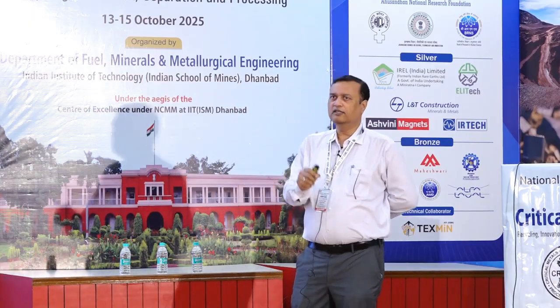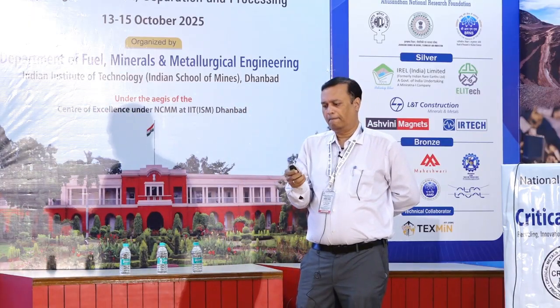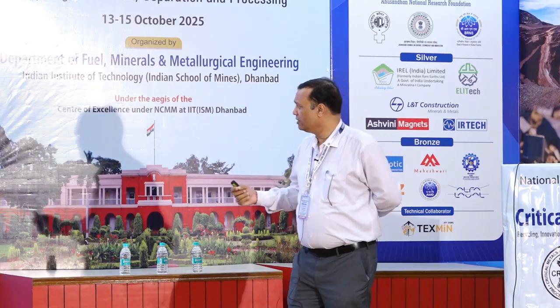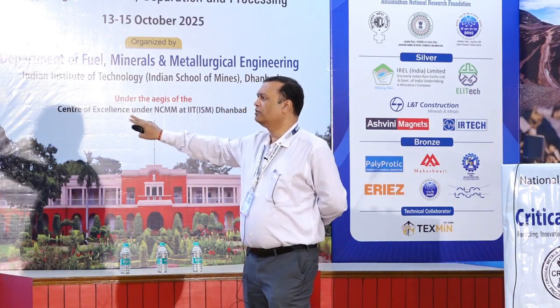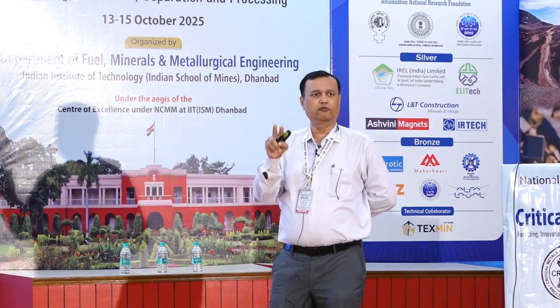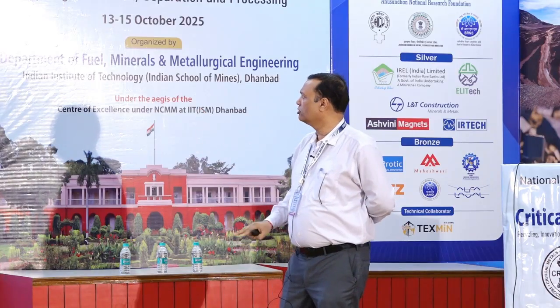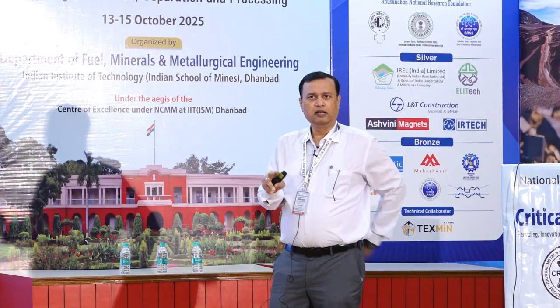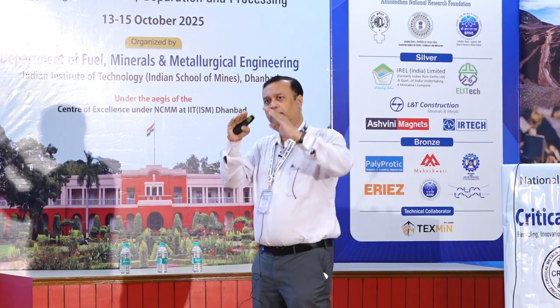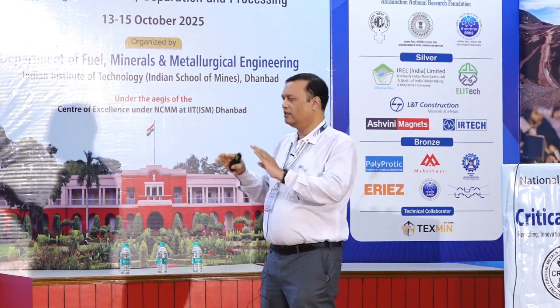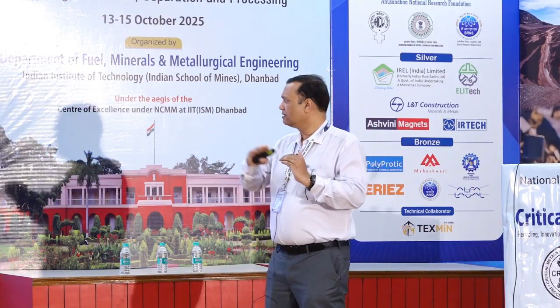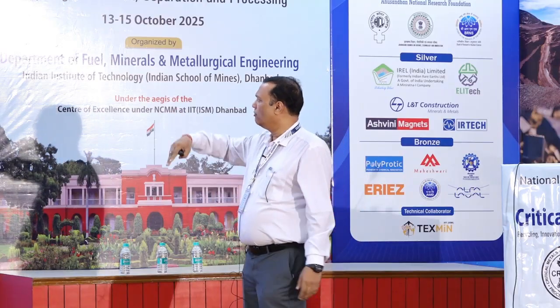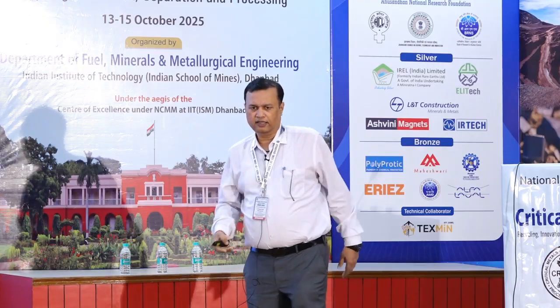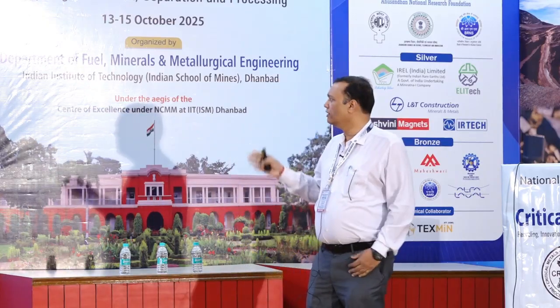And if you want to increase this operating temperature, say if you want to go up to 500, this kind of microstructure should be stable up to 500 degrees centigrade. The problem comes when we go above 400: a diffusion reaction starts taking place where the Sm starts going towards the cell boundary and copper starts coming inside the grain. That destroys the total magnetic property of 217 magnets.